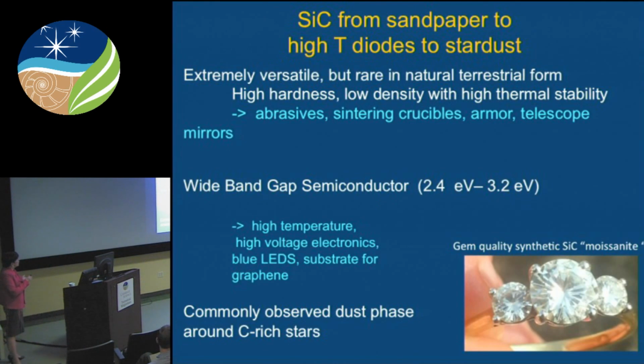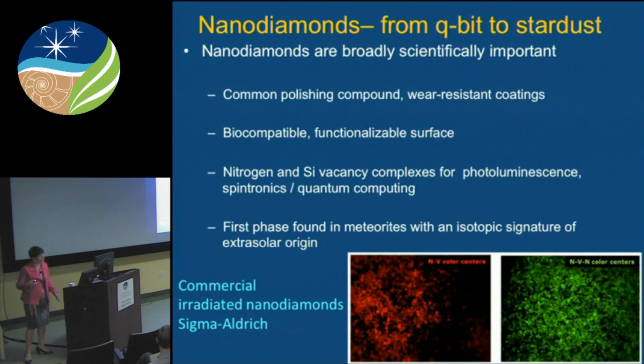So these two materials, silicon carbide and nanodiamond, are actually important, not just to the planetary scientists and the astronomers, but also to the materials physicists and the electronics industry. Silicon carbide has, for a very long time, been industrially significant. So it's, of course, very hard and has high thermal stability. It's used for sandpaper. It's used for crucibles. It's used for telescope mirrors. It's used for armor. Electronically, it's interesting because it's a wide bandgap semiconductor that you can use at high temperature. And cosmochemically, it's a significant phase because this is a commonly observed phase that condenses around carbon-rich stars.